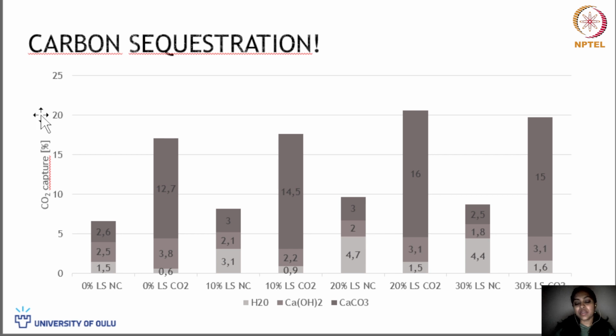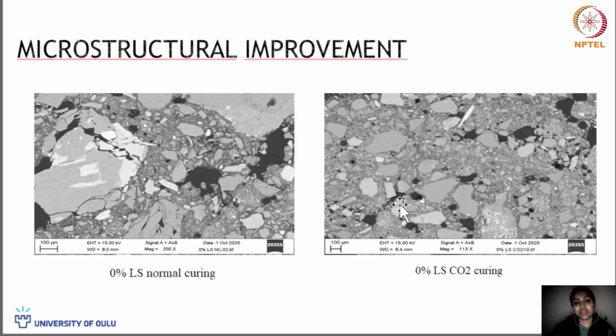Talking about carbon sequestration, you can see that CO2 sequestration efficiency improved with the addition of ladle slag in this material, but it's not so much seen from these values, which are from thermogravimetry analysis. It shows the percentage of CO2 that is captured in different compositions. And it was obviously seen that with the CO2 curing, there is improvement in the microstructure. There are fewer pores, especially on the surface layer compared to the interior.